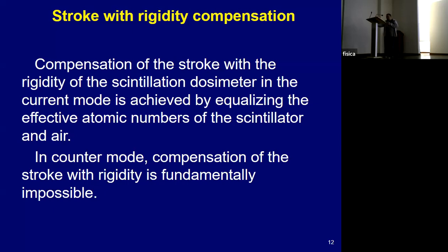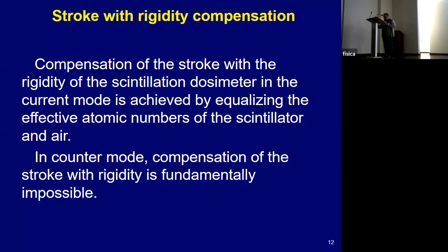A good way to compensate for the energy dependence of the detector sensitivity is to use a combined scintillator in which a finely dispersed inorganic scintillator is incorporated into an organic one. In practice, this is realized by introducing 0.4% of zinc sulfide activated by silver into the scintillating plastic, which equalizes the effective atomic numbers of the combined scintillator and air. The counter mode of operation for the scintillation detector is mainly used for the purposes of radiometry